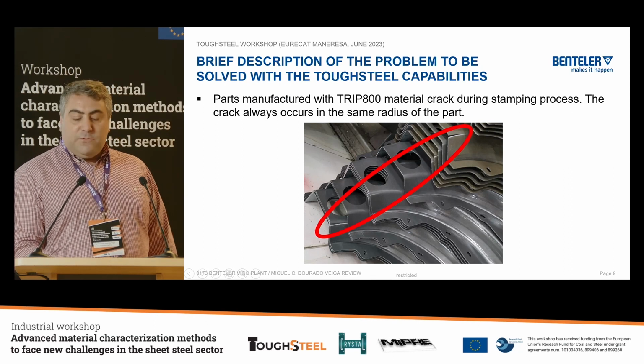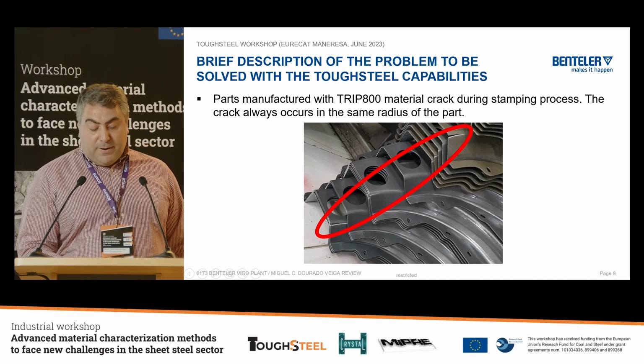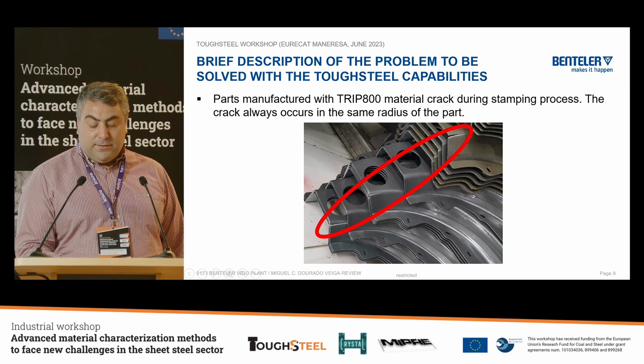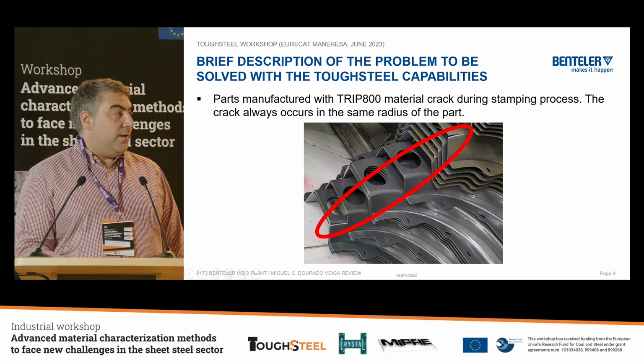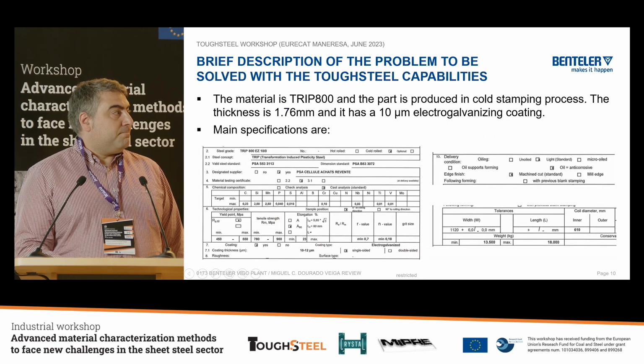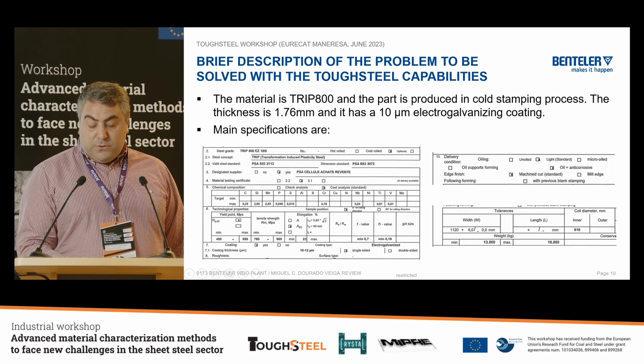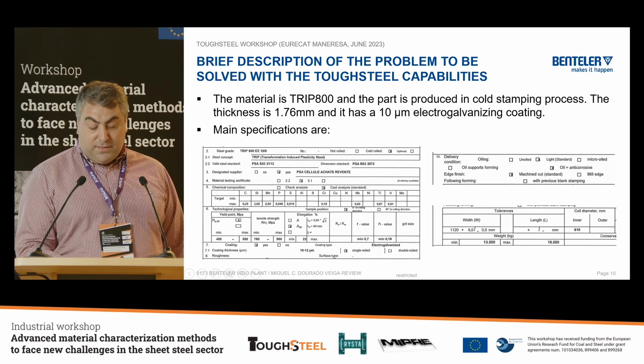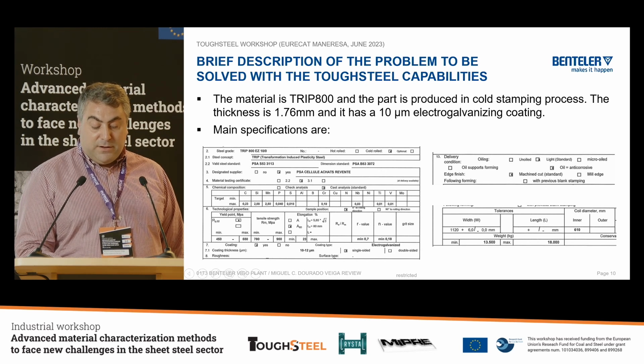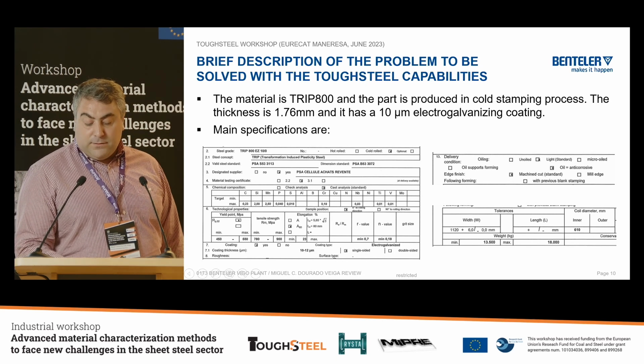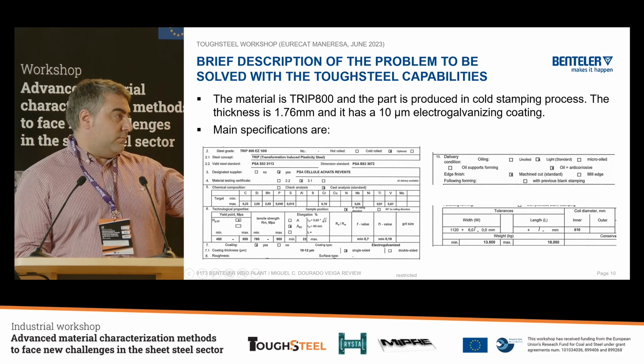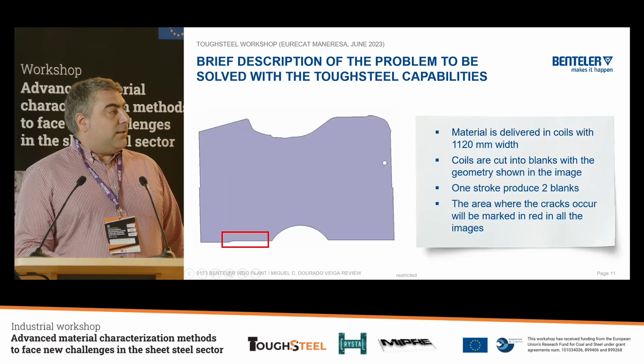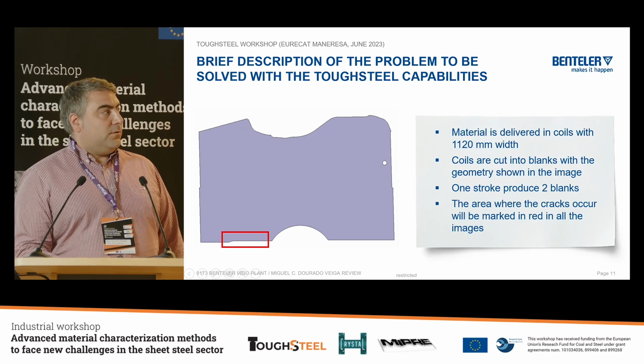Some brief description of our problems. The parts are manufactured with TRIP800 material, and it cracks during the stamping process. The cracks always occur in the same radius of the part. The part is produced in a cold stamping process. The thickness is 1.76 millimeters, and it has a 10 microns electrogalvanizing coating. The main specifications are that, but I guess it's not too important.